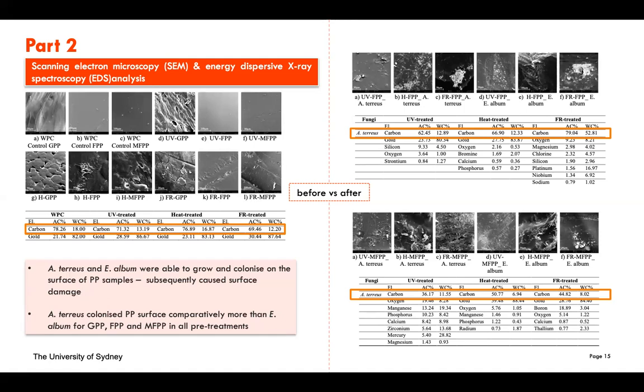And then we also did the EDS. EDS is energy dispersive X-ray. It helps to determine the percentage of the elements present on the surface of the polymer. Here I want to see the atomic concentration, especially of carbon, being reduced. You can see that in the control, we have about 78.2%. But after the incubation, the carbon concentration has declined. So this indicates that the fungi are able to consume the carbon source from this polymer after certain periods of incubation, due to the decline in the carbon number.